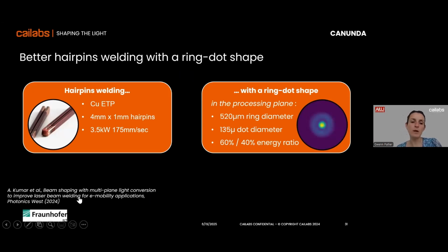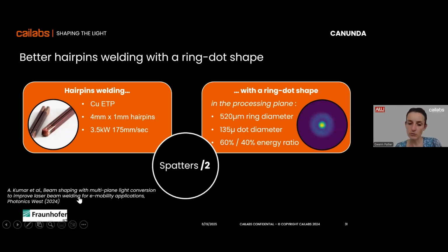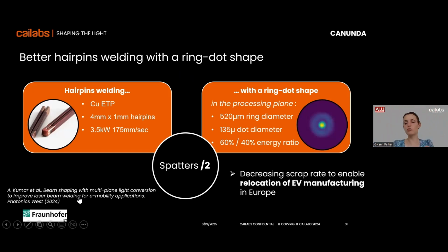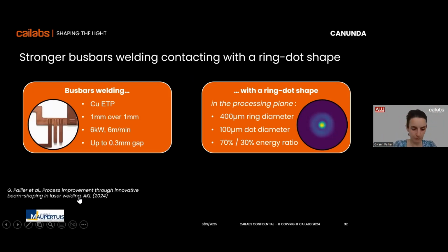So we worked on hairpin welding, and the idea was to work with a lot of soiled samples, misaligned or with fingerprints and stuff like that. And in all cases, what we demonstrated is that by shaping the beam, you can reduce the spatters a lot because you are stabilizing the melt pool. So we divided the spatters by a factor of 2, which was important to decrease the scrap rate.